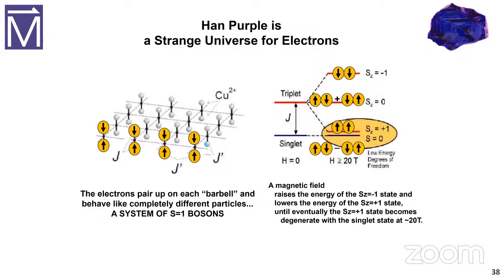Well, in zero magnetic field, you have a singlet, which is up, down, minus, down, up, times one over square root of two. And at higher energies, you have the triplets, which are either both spins down, both spins up, or up, down, plus down, up. And if you turn on a magnetic field, you can imagine that the energy of this state doesn't change. The energy of this state doesn't change. This one goes up in energy, and this one goes down in energy. So a strong enough magnetic field, in this case higher than 20 Tesla, raises the energy of that state, spin minus one, lowers the energy of this state, spin plus one, and eventually this state becomes degenerate with the singlet state at around 20 Tesla.